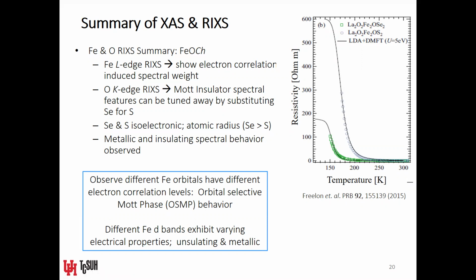You'll recall that that high energy spectral weight appeared at some incident photon energies, but not others. That's evidence that that spectral weight is excitonic in nature. If it's excitonic in nature, then it's related to the interaction between electrons. So this is why we say that it's a correlation-induced spectral weight, which is what you're going to see in an insulator, but you didn't see, for example, in iron metal, and you didn't really see clearly in the iron pnictide parent compound. In the oxygen edge RIXS, what we showed you was that you can actually go from the selenium to sulfur, and you can tune the spectral features a bit.